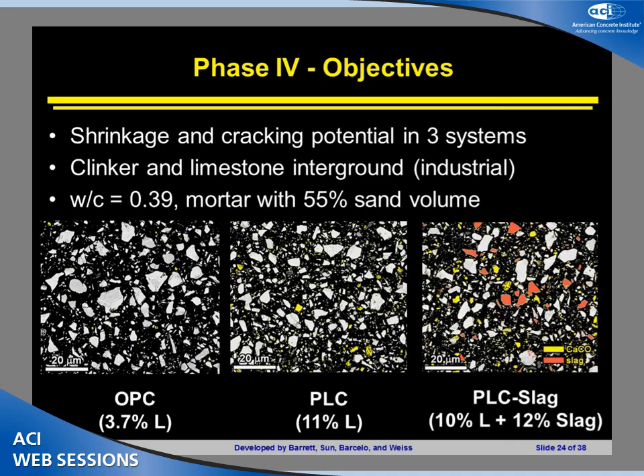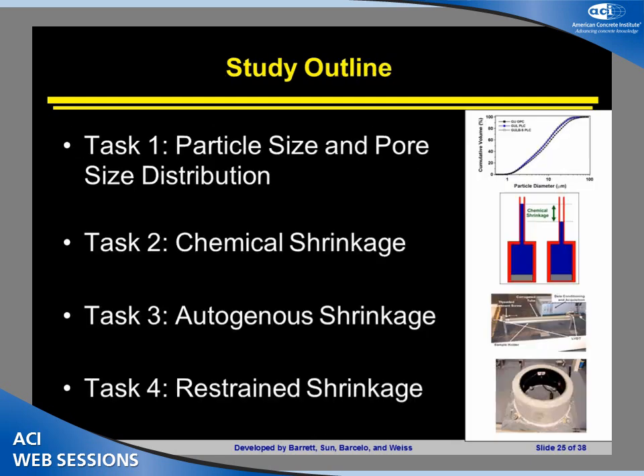One of the things that's interesting to note is if you look at the OPC system, you see a lot of very large particles. And as you start to go to the PLC and the PLC slag particle systems, some of those big particles will disappear. You'll see a lot finer particles. Most of these finer particles are the yellow particles, which are the limestone. And then you also see some of the slag particles interdispersed, as we see over here.